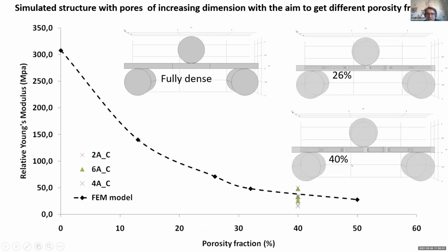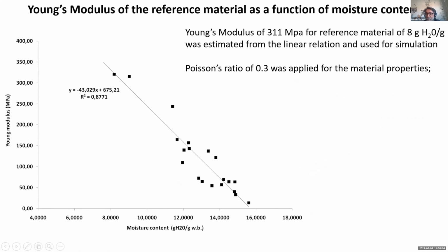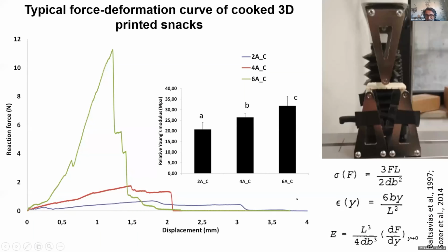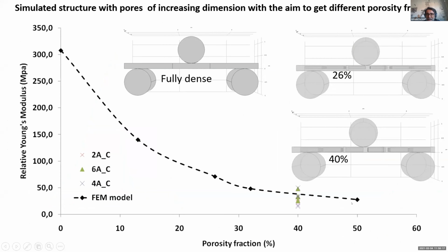40%, I want to go back just 1 second, because after cooking, we obtained a porosity fraction more or less equal to 40%. These are the experimental data, and the dotted line is the estimated property. So at 40% of void, we are able to obtain the same result. That means that if we work in this direction, absolutely we need further experiment, but it is possible again to estimate texture properties.